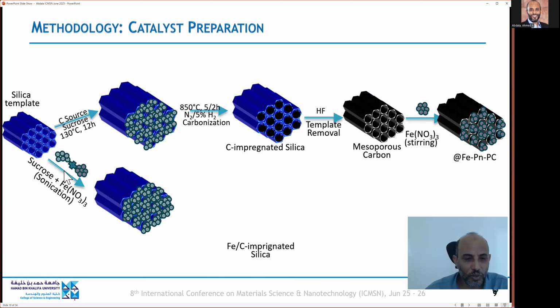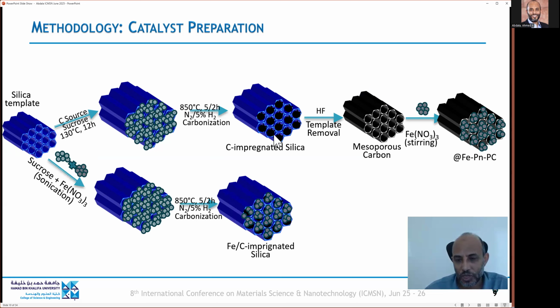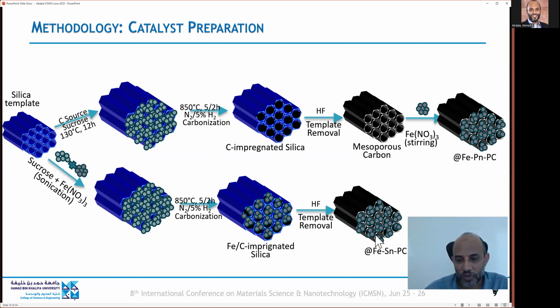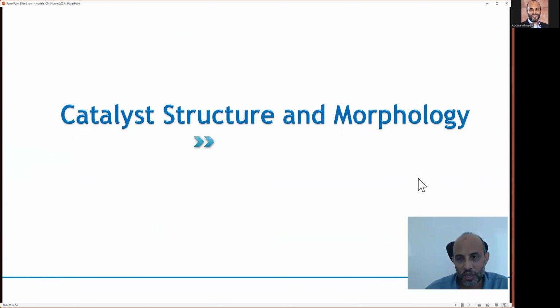Alternatively, we can do a one-step impregnation of the carbon source and the iron source via sonication. And then after that, we can do the carbonization and the reduction of the iron nitrate to form iron on carbon that's impregnated in the silica. And then we can remove the silica template using hydrofluoric acid to end up with carbon and iron nanoparticles assisted by sonication in porous carbon. So we have both confinement and sonication-assisted iron nanoparticles.